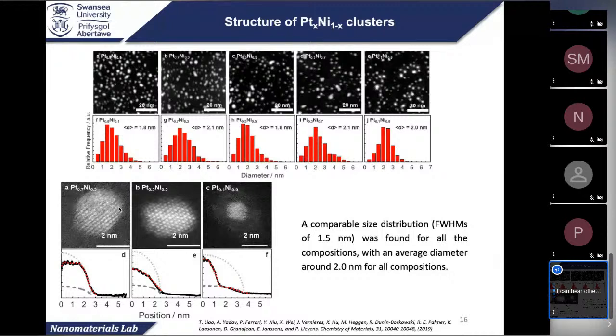For the 50/50, which is in the middle, you have a very well alloyed structure, but you can still see some small domains with nickel-rich areas.